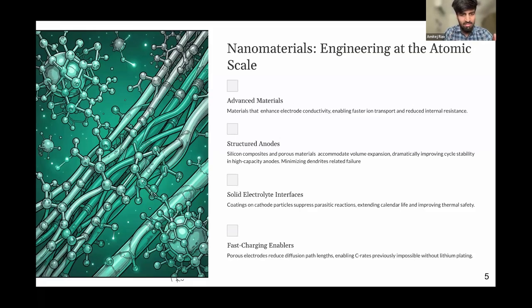So porosity is very important, but again, the trade-off should be that there shouldn't be excessive solid electrolyte interface formation, because it would lead to capacity loss, and by default the cyclic life would reduce. So these are the different trade-offs of how to use materials. It's a very delicate balance of material properties and their impact on the electrodes, the overall cell and the battery technology.